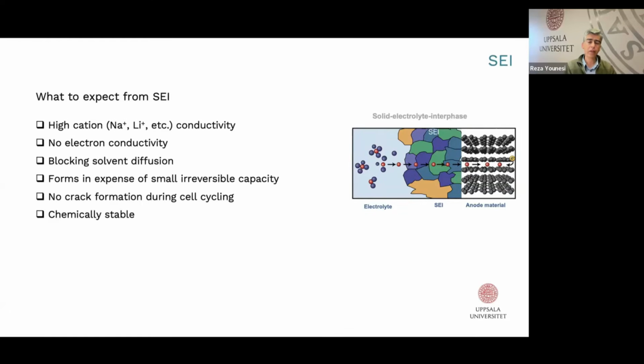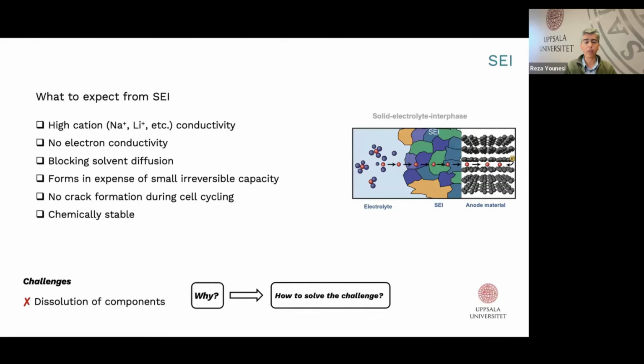One specific challenge here is the stability and chemical stability of SEI, because when SEI forms, all those species that form it could actually be dissolved in the electrolyte solution. As an example, if lithium fluoride or sodium fluoride is one SEI species formed during electrolyte reduction, it could be dissolved back into the electrolyte solution.